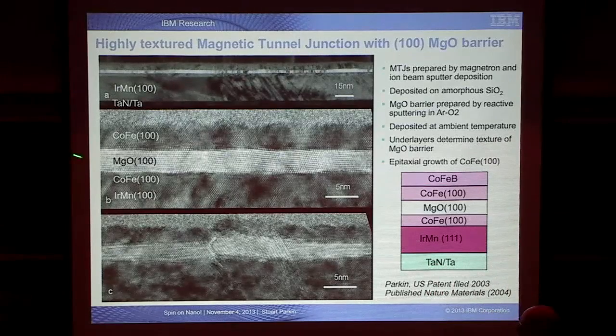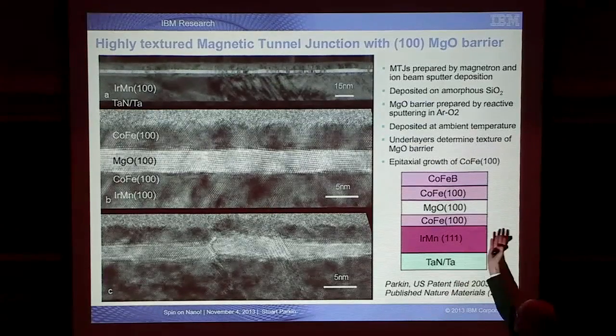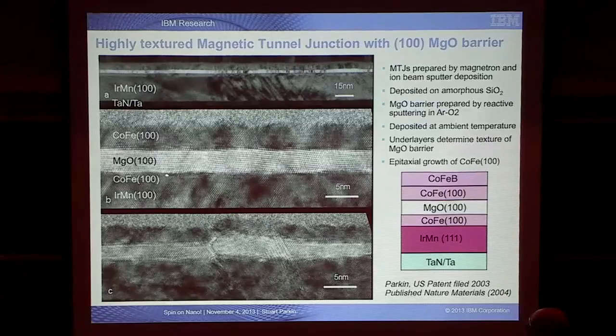It's called magnesium oxide, a simple cubic material. And can you see in this, again, this is a transmission electron micrograph through the multilayer. You can see in this case, the insulating material also, you can see these atomic layers. Now it's crystalline. And it turns out because it's crystalline, the wave function symmetry of the electrons that are tunneling